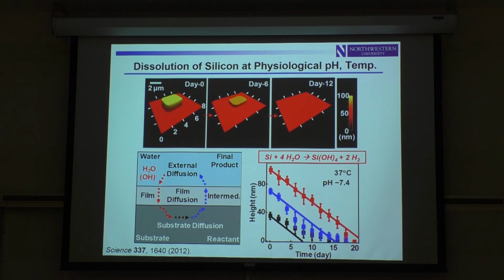But it turns out that there is something happening, it's just not much, but that not much tends to be important, increasingly so, as you miniaturize the dimensions of the silicon structures themselves. And in fact, if you take these silicon nanomembranes that I was talking to you about before, and you immerse them in PBS solution, water with some electrolytes, at physiological conditions, it actually disappears on a two-week time scale, roughly, due to this reaction. So it's silicon reacting with water to form silicic acid, a very, very slow rate of reaction, but again, you have a very tiny thickness of material.